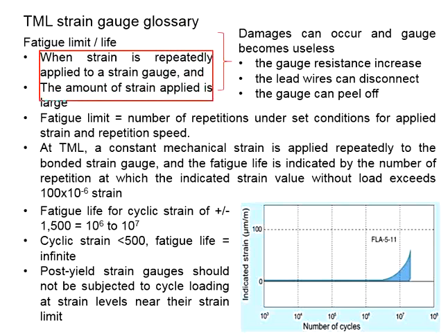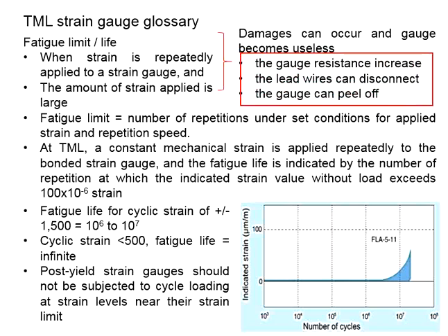When the strain is applied repeatedly at a large magnitude, one or more of these can happen. This includes the gauge resistance increasing, the lead wire disconnecting, or the gauge peeling off. Any of these happening will give you an inaccurate result or no result at all. Now, if your specimen is subjected to fatigue load, that means there will be changes of the strength over a period of time in numerous cycles, you will need to check for the fatigue limit.